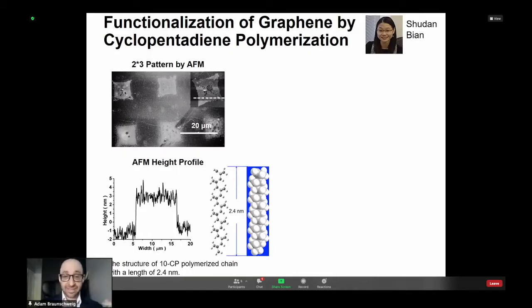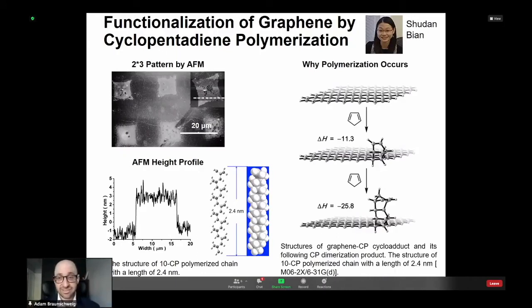But so we went back to the Houk group, and they did some calculations for us. And the way we explain this is, even under mechanical force, it's hard to get this first reaction to go because you have to disrupt the stabilizing conjugation of graphene, but you can get it to go. But upon the first Diels-Alder reaction, you get a new carbon-carbon double bond forming right here. That carbon-carbon double bond can then participate in another Diels-Alder reaction, and then the polymerization takes off. So you get, instead of just a single cycloaddition reaction, multiple cycloaddition reactions because you have the increased favorability of the reaction plus the force driving that reaction forward. So after the first initiation event occurs, polymerization just takes off as a result of the force being applied to the system.